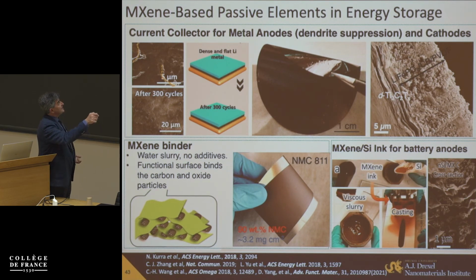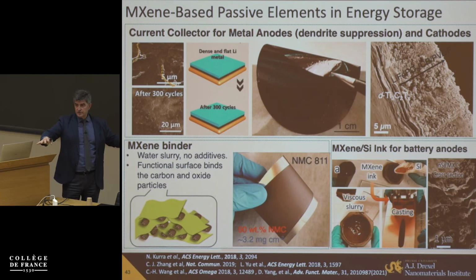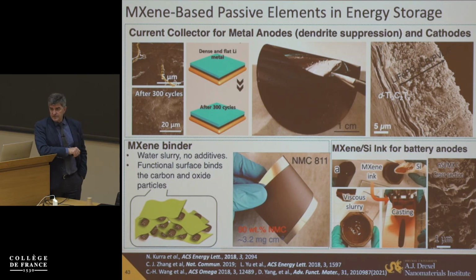Moreover, there has been work from probably at least a dozen different groups around the world showing that MXene layers, unlike copper, suppress growth of dendrites, and particularly working with collaborators at Drexel University, we showed that growth happens laterally, totally on the surface here when you grow it, even at pretty high rates. They have a hypothesis from DFT that hexagonal lithium is formed a few atomic layers thick to accommodate the strain and follow this growth. It's still to be experimentally confirmed.